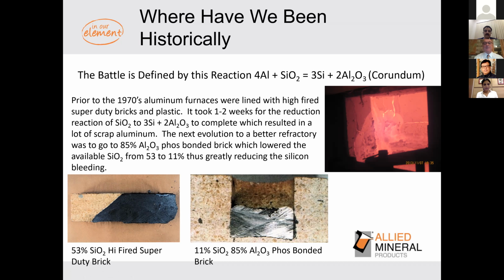So what did the industry do? Well, we migrated to less silica. So we jumped, even though you don't need it because of the low melting point of aluminum, but we needed something with lower silica. So we went to an 85% Phos bonded bricks. And we dropped from 53% silica to 11, effectively reducing the amount of silica that can be reduced. And the phosphoric acid that was used to make the bricks, again, lowered the porosity, less surface area, because you have less pores for it to penetrate, less open porosity for the aluminum to travel into. So this migration happened and worked all the way through the 80s and late 70s.